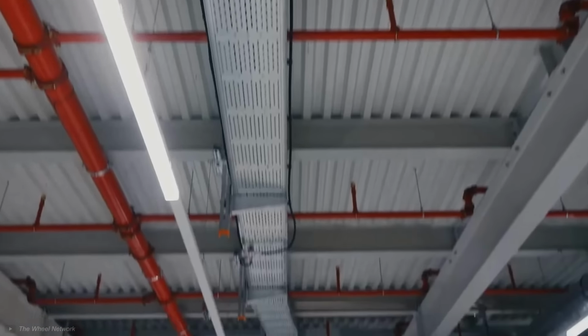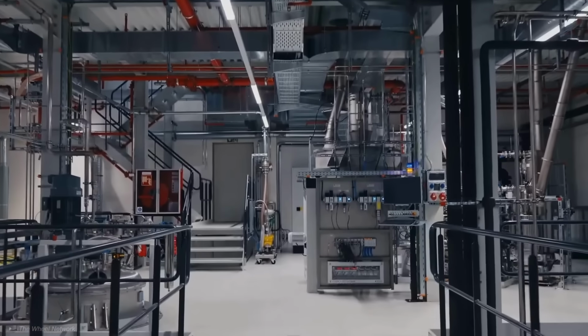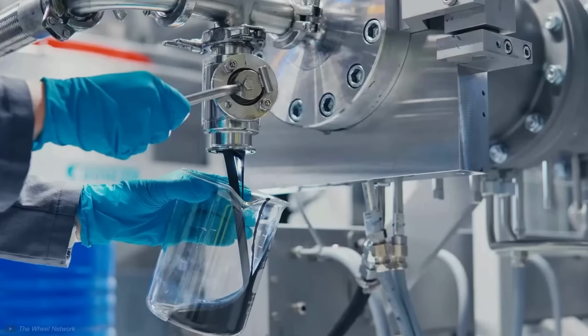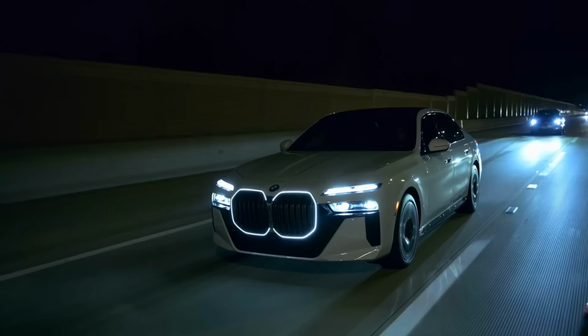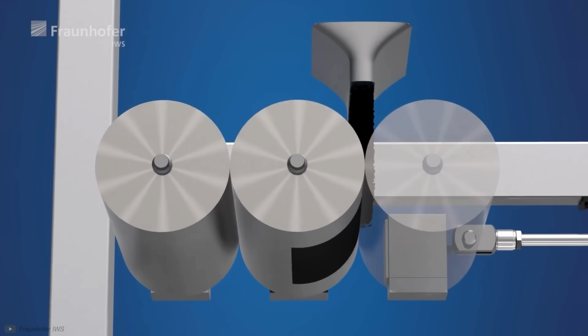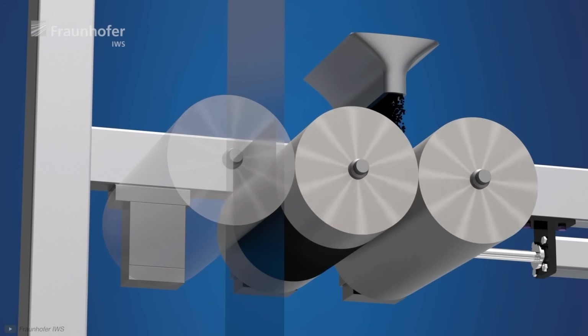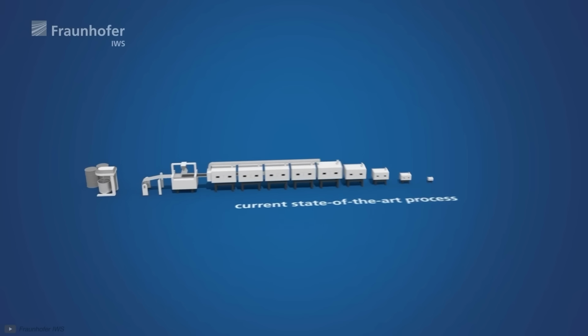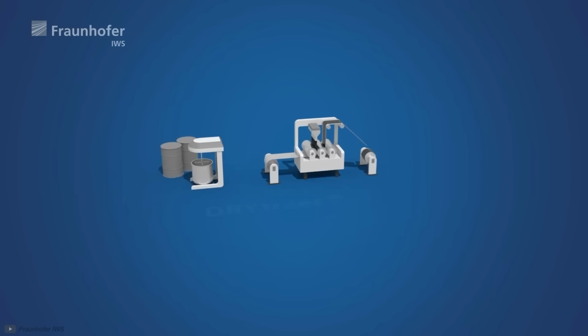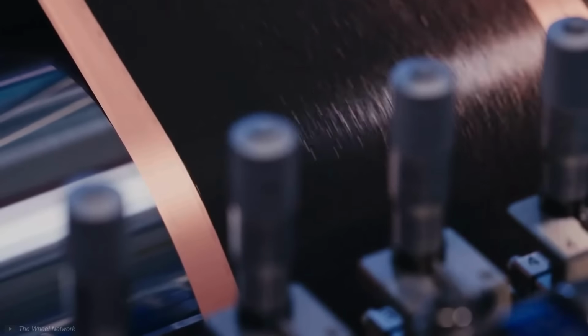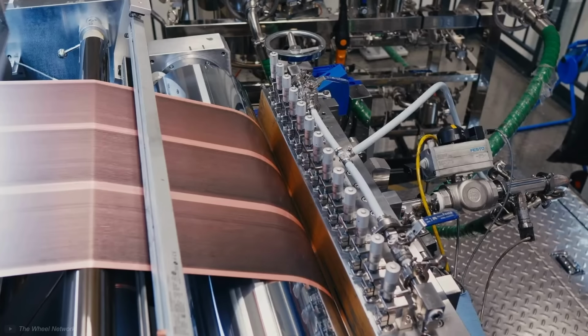In fact, the relatively smaller amount of investment into wet electrode manufacturing pipelines in USA and Europe might actually give a competitive advantage when transitioning to dry electrodes, though I wouldn't rely on the rest of the world staying behind for very long. What makes this all even better is that not only does the dry electrode manufacturing reduce cell costs and remove the slow drying processes, the batteries it makes can also be even better than the ones made using wet coating processes. One big reason for this is something called binder migration.